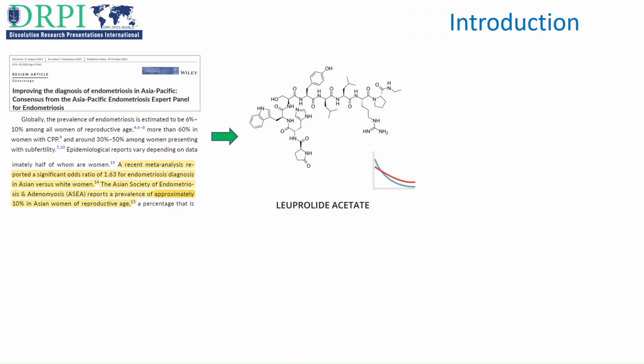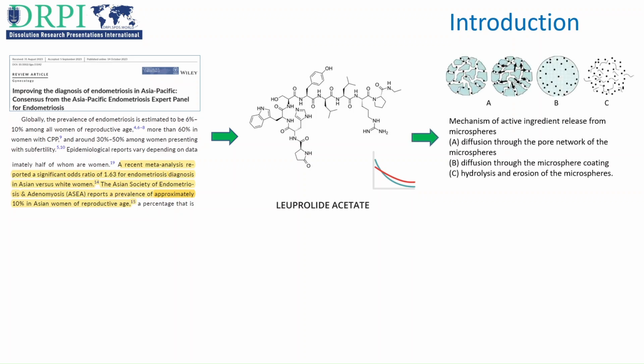However, leuprolide acetate has a short half-life of about 3 hours. To ensure consistent drug release with extended dosing intervals, a sustained-release drug delivery system with a therapeutic duration of several weeks or months is required, such as microspheres. Microspheres release active agents through several mechanisms, including diffusion through the pore network, diffusion across the microsphere coating, and hydrolysis and erosion of the polymer.